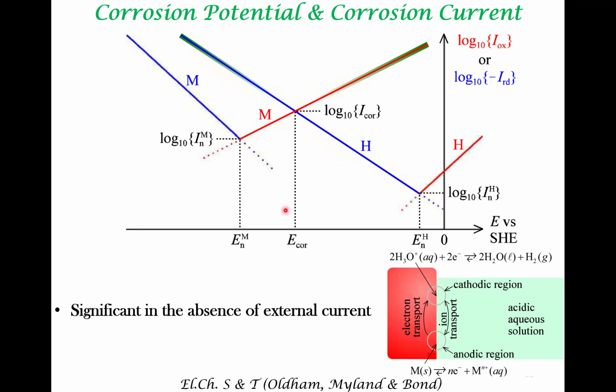Just to re-emphasize, E corrosion is obtained while the Tafel plots can be plotted by driving external current. E corrosion is most significant in the absence of external current. In the absence of external current, the rate of generation of electrons here has to match the rate of consumption of electrons. So when you look at this curve, you have to connect to two particular aspects: how we obtain the entire plot, that is obtained by